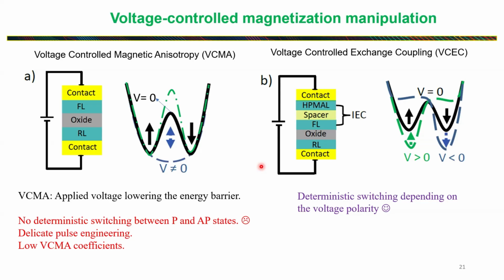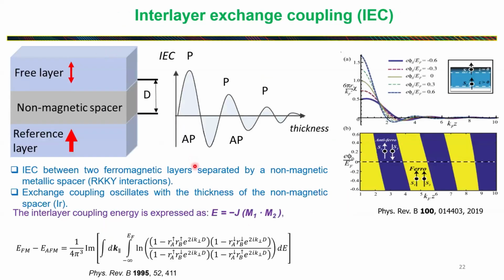spacer between the two ferromagnets. And what we found is that with an electric field, you can actually change this RKKY coupling. Ideally, this is how the RKKY coupling looks when you change the thickness of this metal layer between the two ferromagnets, and this is how it looks.